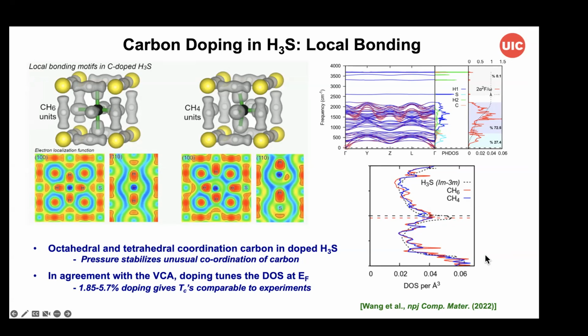The full Tc calculation has not been done for a supercell that is identical to what we have in the VCA model for optimal doping, but there's more or less consistency with the data so far. So we think we now have more or less a local bonding picture of the carbon in the system, although a number of questions remain, including the stoichiometry and defects around the carbon and so on. So this is very much still an active area of research, both experimentally and theoretically.